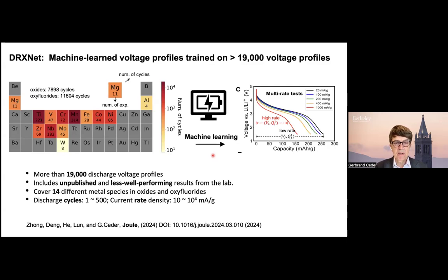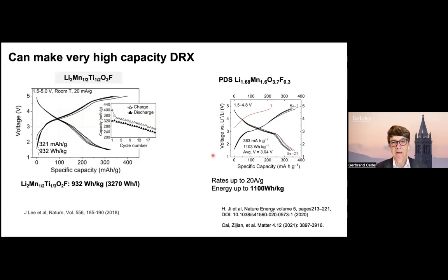There's so much data that we recently published a paper where we showed you can do machine learning on these data, and you can actually predict voltage profiles as a function of cycling for many of the different DRX chemistries. You can make very high capacity DRX materials. For example, here's a highly fluorinated one. This is a manganese 2+ to 4+ redox couple. You can go over 900 watt-hours per kilogram. Here's a partially disordered spinel, which is over 1100 watt-hours per kilogram with extremely high rate capability.